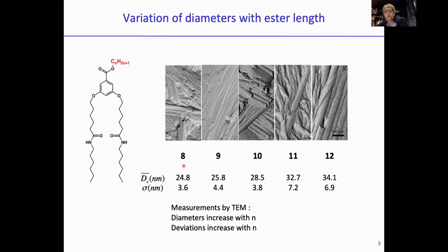And you can see when the number of carbon in the chain increases, when the length of this ester increases, then the diameter of the objects, which were measured on a statistically decent number of objects, I would say 200 tubes, then we can see that the average outer diameter increases with number of carbon atoms. And you can see also that we are able to measure the polydispersity. So the variation of the diameter increases with number of carbons.